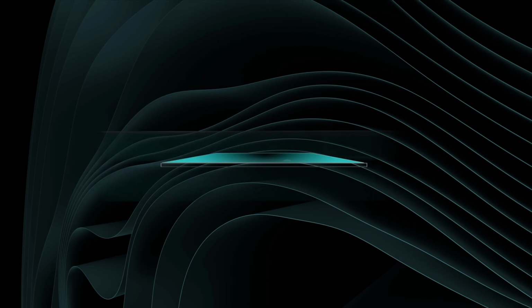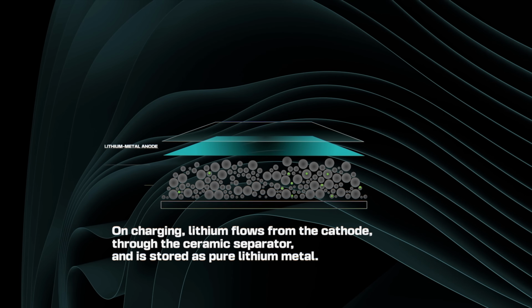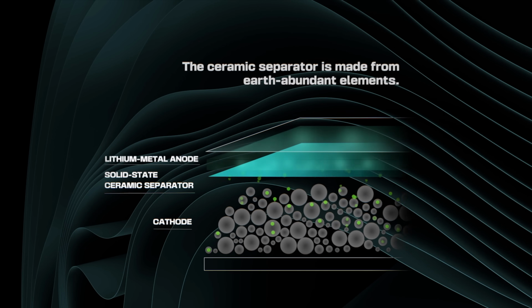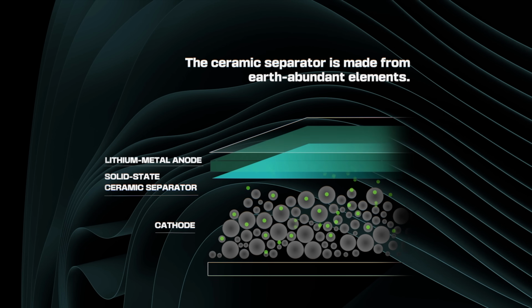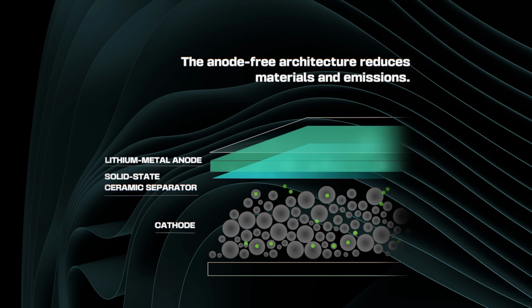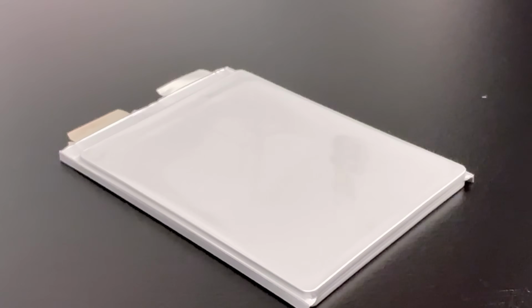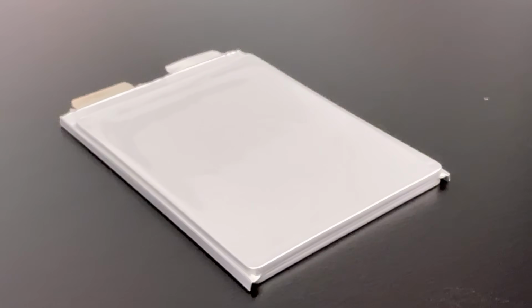Most ceramics are brittle. They crack when the battery expands, and they can't stop dendrites without massive pressure. QuantumScape developed a flexible ceramic that bends without breaking. It's thin enough to let lithium pass through efficiently, but tough enough to physically block dendrites. And here's the key, it works at soda can pressure. That separator is the reason this entire technology exists. Without it, everything else falls apart.